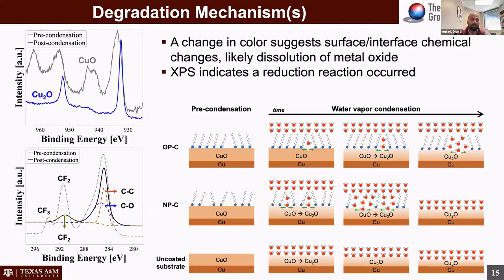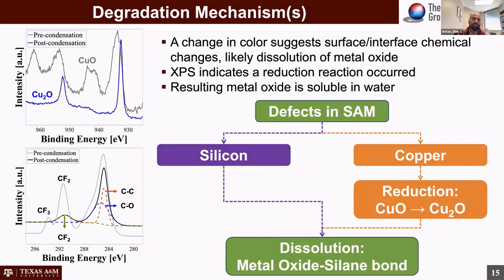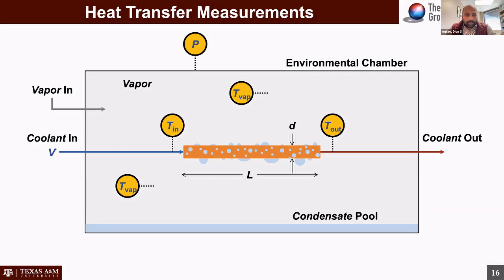As you eat away the oxide, you're basically removing the coating from the surface because the coating is bonded to that oxide. And so a very simplistic view of that mechanism is you have defects, and irrespective of the substrate, the end result is dissolution of the siloxane bond, whether it's a siloxane bond, Si-O-Si, or a Cu-O-Si bond with the copper surface requiring an additional reduction reaction, likely from CuO to Cu2O. Now, that's a lot of surface chemistry.